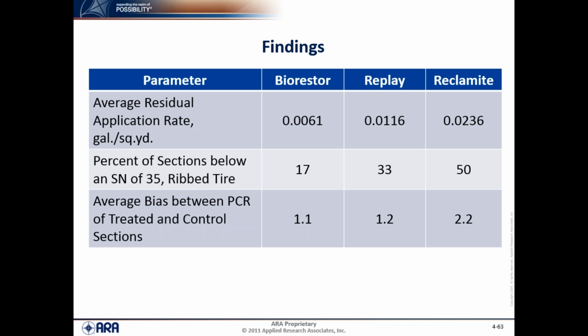And so you can see that as the residual application rate increases, which is what we would expect from our data measured by the department, the percent of sections below a skid number of 35 increases. Conversely, we see less distress and a higher PCR value between the treated and control sections with the higher residual application rate. But these are the average application rates used by the individual suppliers, which were initially determined not based on the experience itself, but I think through coordination between the supplier and District 7. I'm not sure how those rates were evaluated or determined, but that's just the average between each of the individual projects.